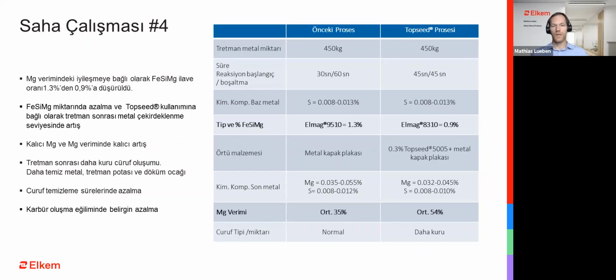Case study number 4. There has been a reduction of ferrosilicon magnesium from 1.3% to 0.9% due to an increase in the magnesium yield. The magnesium yield seems to be low, but it is a very special process in a small historic foundry with a 2-step treatment at temperatures of 1500 to 1530 degrees. At first, the FSM treatment is done with 300 kilograms, and then another 150 kilograms of melt is tapped into the ladle together with an in-stream inoculation. And then the pouring is done completely manually directly out of this ladle.